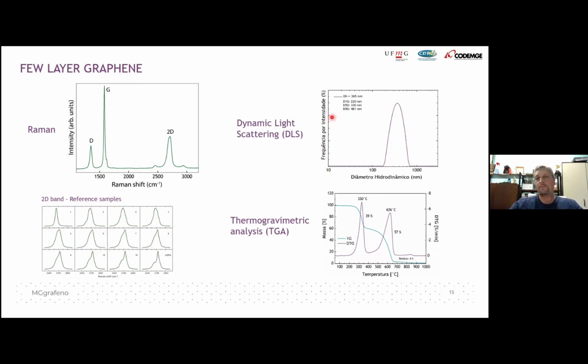I will show why. So this is the dynamic light scattering, which gives you some kind of hydrodynamic diameter. And this is the thermogravimetric analysis, which is quite accurate to give you the amount of graphene that you have, the carbon material at least, and the amount of residue that you may have in your system.